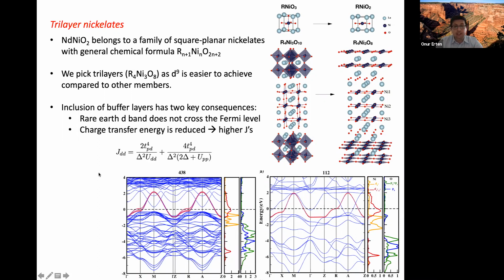And another effect, and this is not necessarily intuitive at first look, is that the super exchange interaction is in this case higher because the charge transfer energy to the oxygens is reduced. And I don't really have much of an intuitive understanding other than that we can look at the position of the oxygen bands. Here it's closer to the Fermi energy, and therefore the super exchange is expected to be large. So two things. One, putting these buffer layers gets rid of the rare earth band and makes it more cuprate-like. And also it reduces the charge transfer energy, which gives rise to higher super exchange coupling.